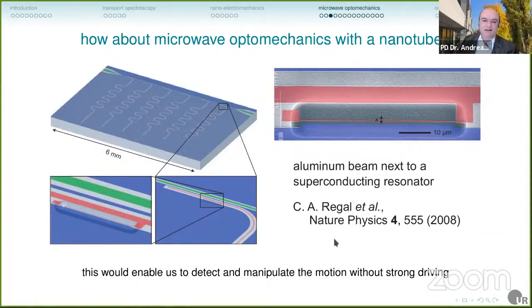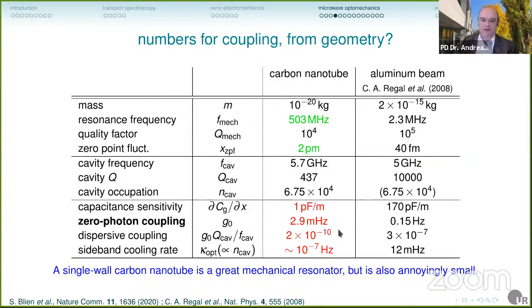I mentioned this is a very well-researched area, so the theory also exists, and we can insert the numbers for a carbon nanotube. And the carbon nanotube is in some respects really great. You can see here the high resonance frequency and also the large zero-point fluctuations of the position, because it's very light. But on the other hand, if we look at the coupling parameters between such a microwave resonator and a suspended carbon nanotube, well, the numbers are abysmal. They are tiny. And that's basically because a single-wall carbon nanotube is a great mechanical resonator, but it's also annoyingly small. What we have here is a mismatch of scales.